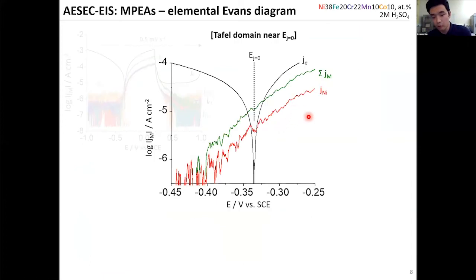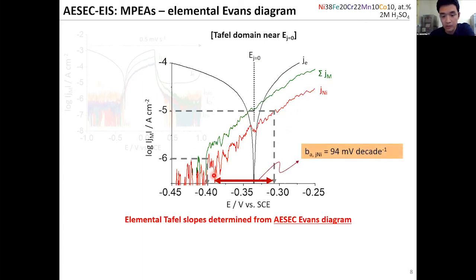And to go a little bit further in this Tafel domain, we can also extract the Tafel slope of each element. Here, an example of nickel: the Tafel slope is around 94 millivolts. What's interesting is that in conventional electrochemistry, we are not really able to define the Tafel slope at potentials more negative than the zero-current potential. Whereas with this technique, as you can see here, over slightly more than 1 order of magnitude, you can see this linearity of the nickel signal. Other elements were the same; I just put the nickel as an example.